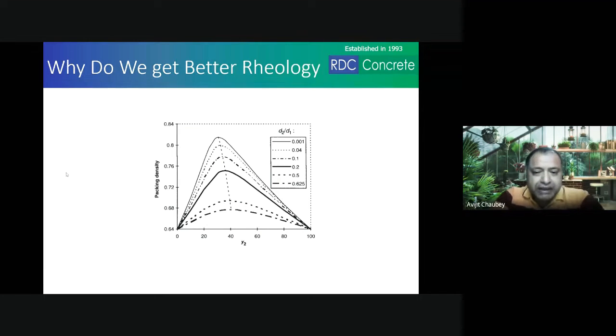But if you see, without gap grading, you will not be making the concrete even today. The concrete that you are making today is actually gap graded. It may not be 20 and sand, but 10 aggregate and sand, you see the middle portion is most of the time missing, 4.75, even if it is a river sand. And if you are making a good river sand, as you call it, where 4.75 particles are also available, 2.36 particles also are available in good quantity, in that case the mix would turn out very harsh and porous. So a good sand is the one where the top sizes are missing. 4.75 is missing, 2.36 is much lesser, and 10 aggregate is more towards 10 size. So when you are putting 20, 10, and sand, most of the middle sized particles between 10 and sand are missing, and that is the reason why you get good concrete.